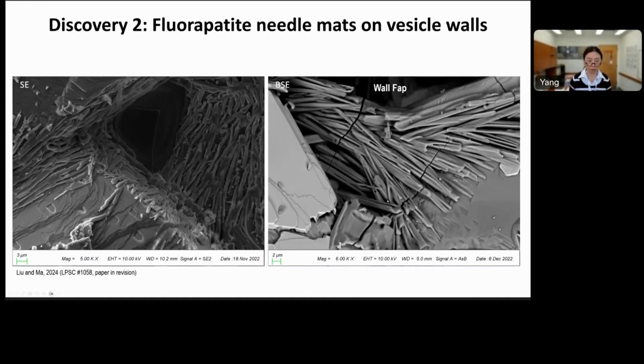So here is the zoom in. The left-hand side is a secondary electron image. As you can see, the fluoroapatite needles are climbing up out of the hole in the vesicle wall, and some of those are actually protruding into the empty space. I didn't show the whole area, but they follow this kind of flow pattern around this hole. The right-hand side shows the empty center of those fluoroapatite needles.